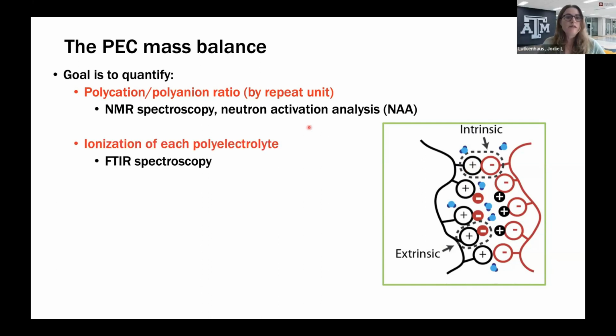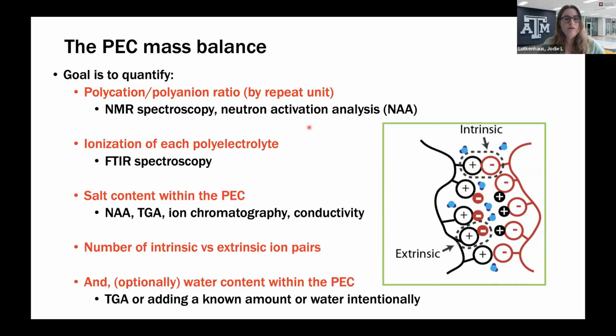Experimentally, we do this by a combination of methods. We can use NMR and neutron activation analysis to analyze the ratio of the polycation to polyanion, because when we mix the polyelectrolytes, what we put in is not always what we get out, because one of our purifying steps is dialysis, where the extra unassociated polyelectrolytes can diffuse out. So we need to know, of that complex we made, what's actually in it.